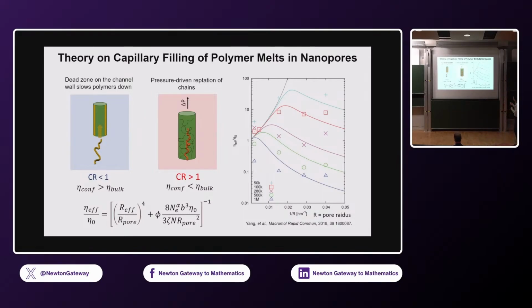And what they see in their experiments, so these dots are experimental results, and the solid line that you see is the model that they came up with, which is shown here. And basically, they define that there are 2 possible ways that the effective viscosity of these polymers can be affected. One is where the polymer is infiltrating, and now there's this layer of polymer that is coated and stuck on the surface of the pore. So that effectively decreases the size of the pore. Okay? So that is going to effectively increase the viscosity.